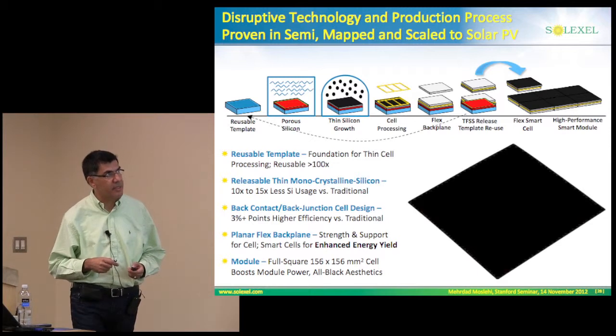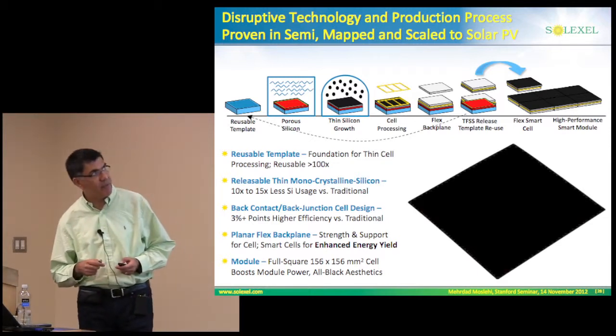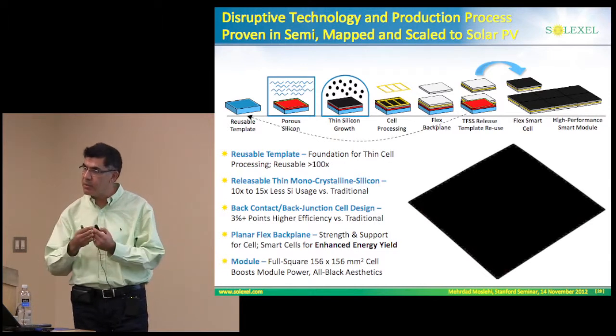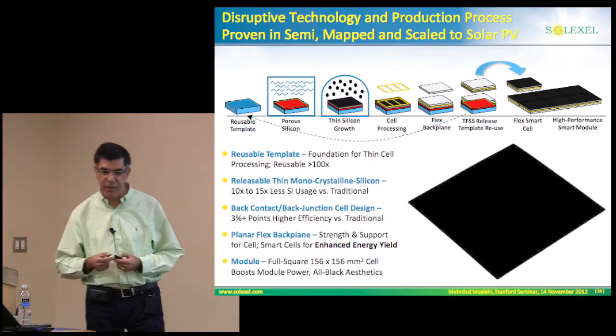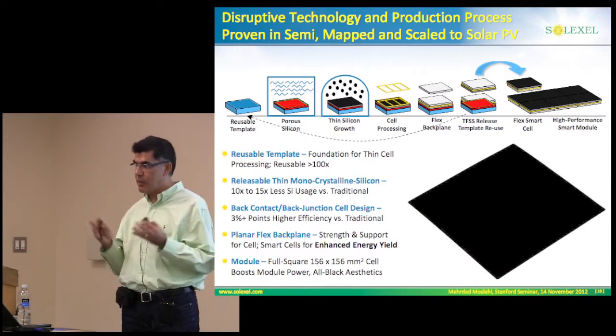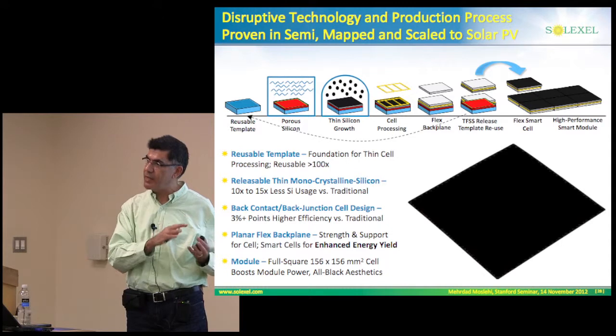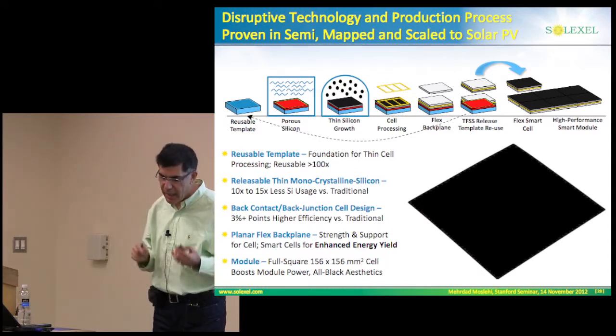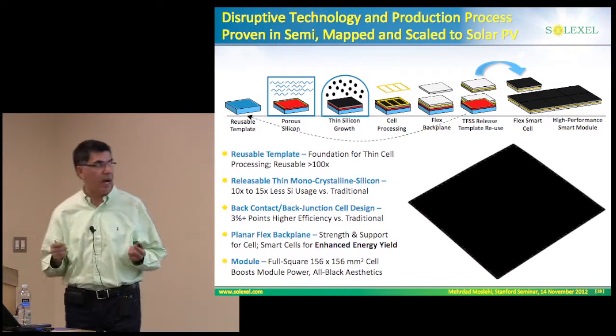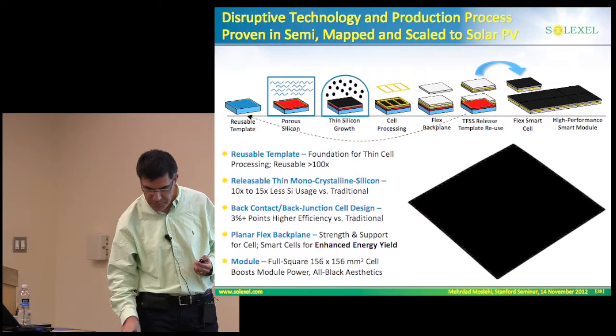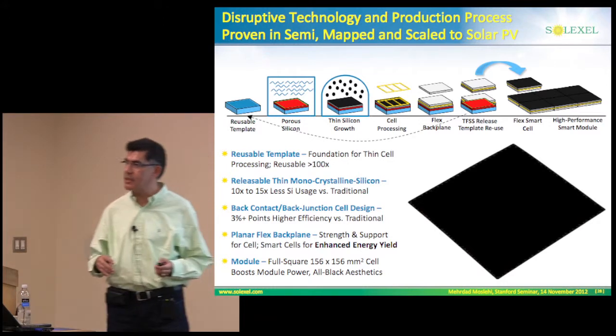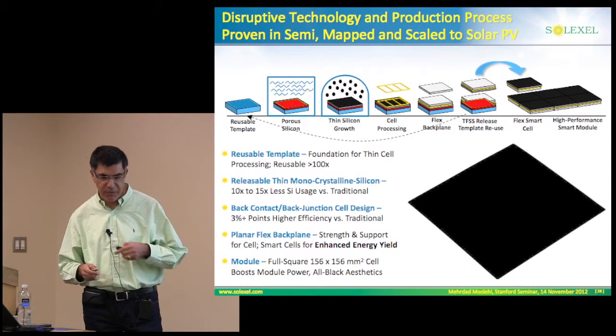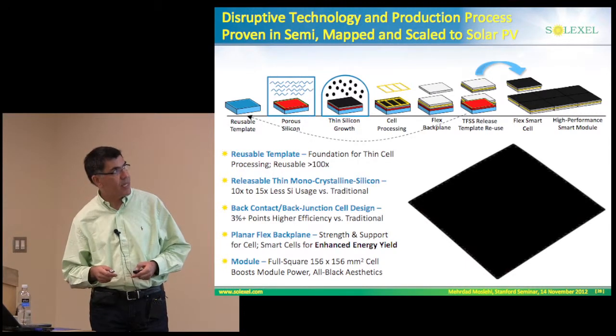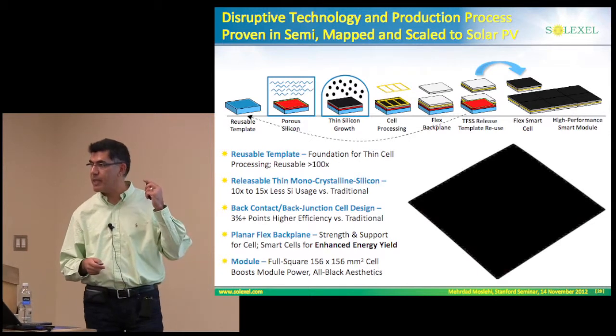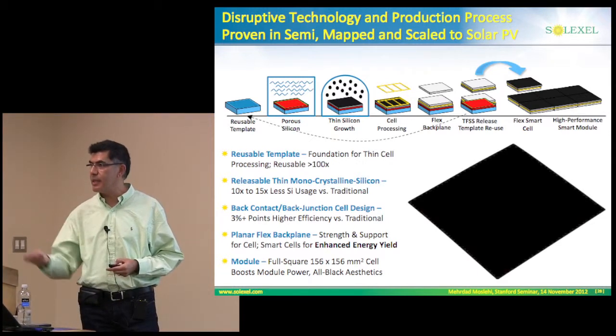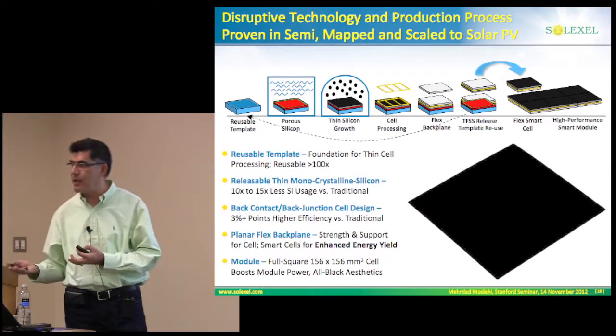And we have essentially mastered that with our manufacturing technology and process. So basically, after we lift off the cell, the sunny side is exposed. There are a couple of steps which involve the texture and passivation. We do the proprietary passivation. Remember, for high efficiency, that passivation is extremely critical, the quality of that. And then we finish the final high conductivity cell metallization. So we don't use any silver. This is very inexpensive metallization, and of course no metal on the front side. The template actually goes back for the next reuse cycle. We reuse it over 100 times. So far we have done it over 50 times.